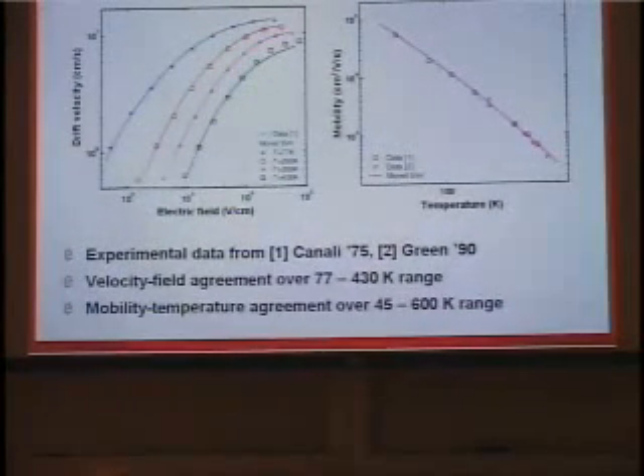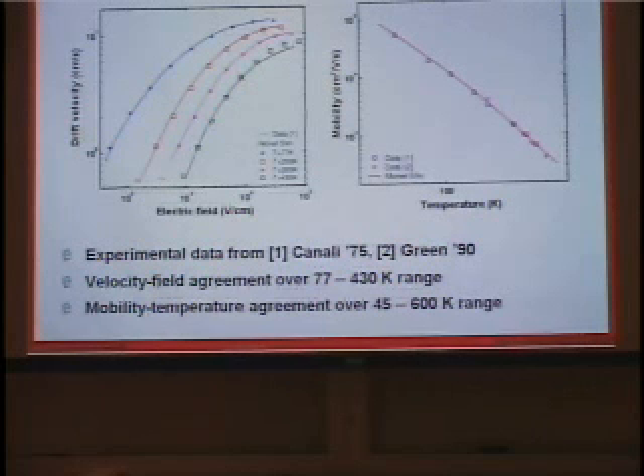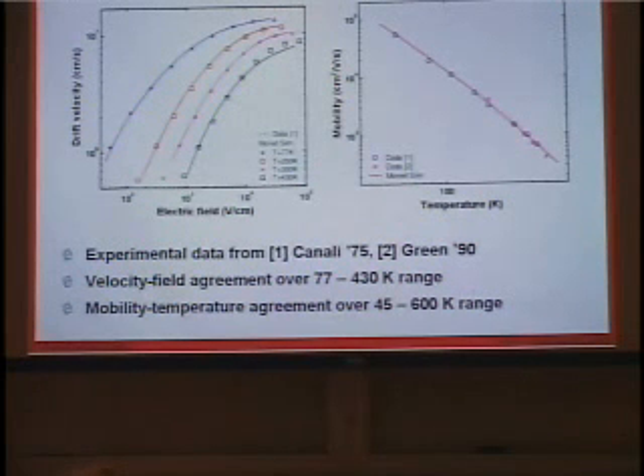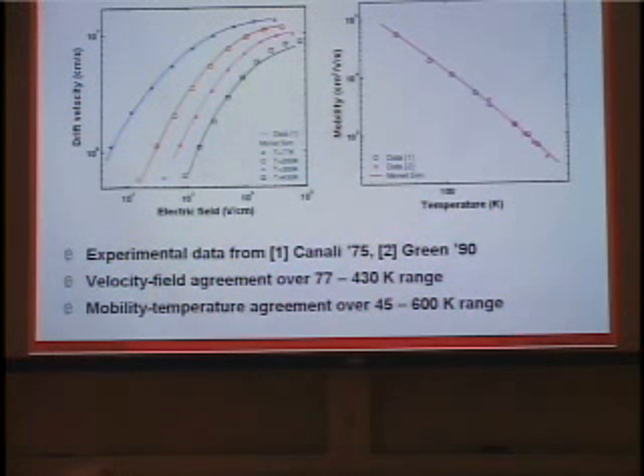Very typical plot. We see saturation occurring at about 10 to the 7 centimeters per second. It's a function of temperature, of course. And on the right, I've got low field mobility as a function of temperature, spanning the temperature range from 45 to 600 Kelvin. So there's a big range of temperatures and electric fields over which this code works quite well. This is in bulk silicon.